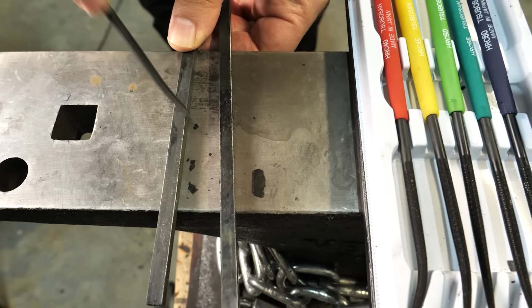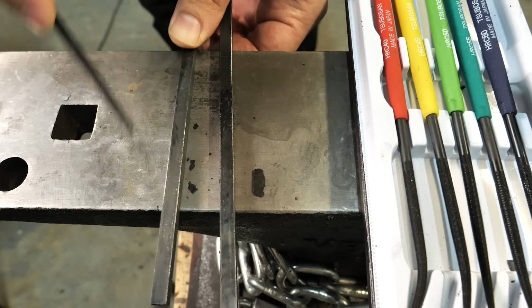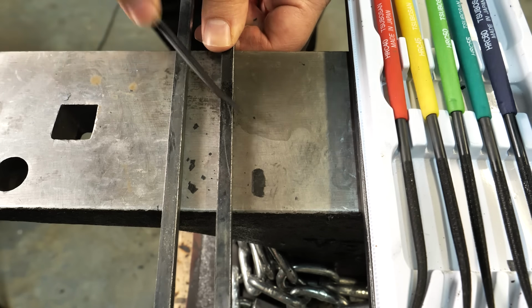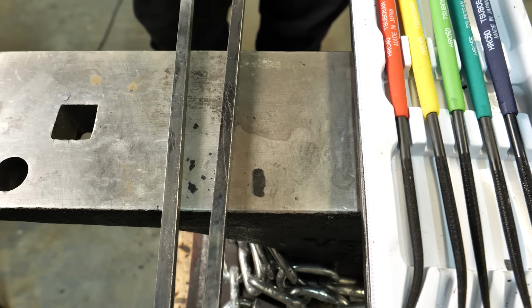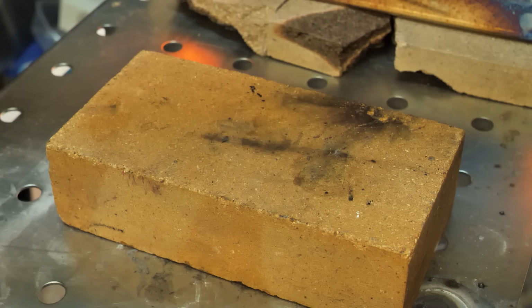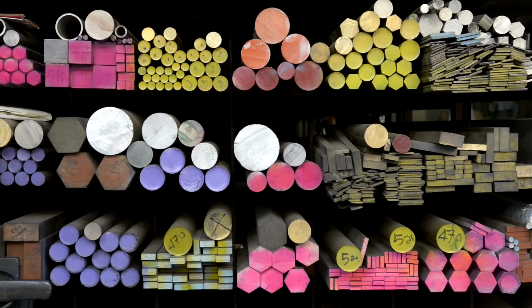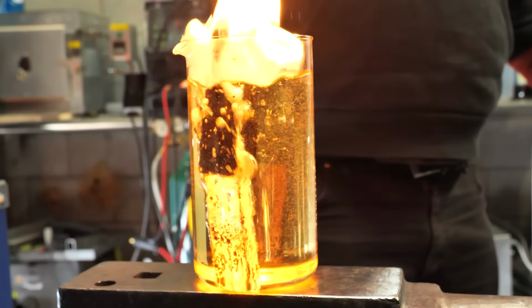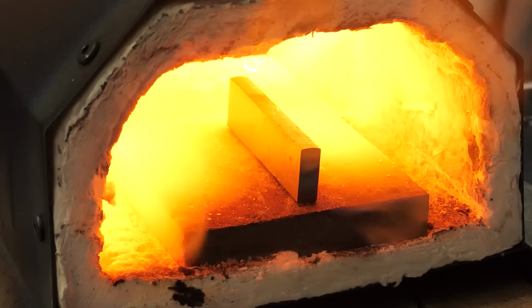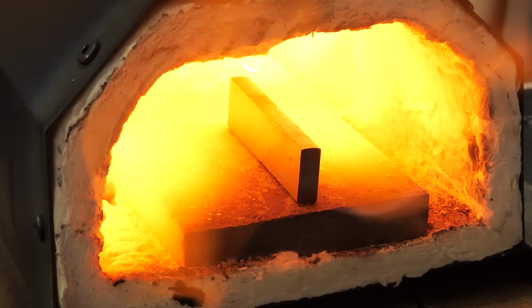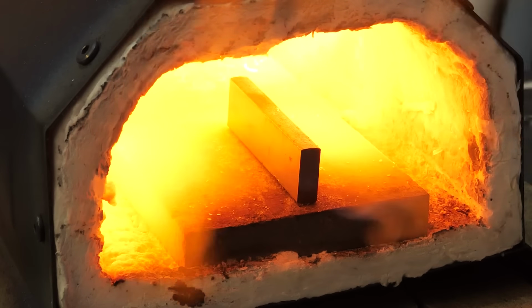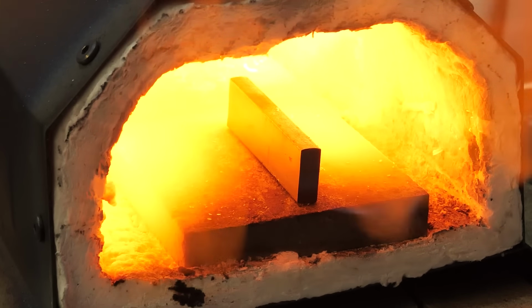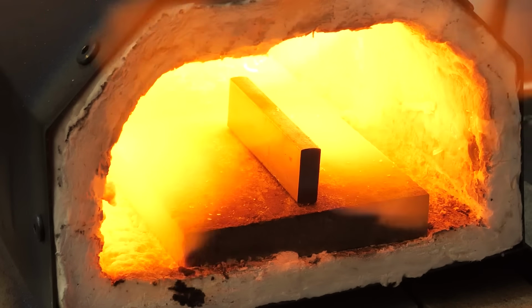When we test these with the files, both were harder than the 65 Rockwell file, so had maxed out the scale, and there was really no appreciable difference. That said, when you're not making steel yourself and are buying a nice commercial alloy, they'll often tell you what liquid to quench it in and precisely what temperature everything should be, as they'll have calibrated it to figure out which is best for that alloy. But in a pinch, either works.